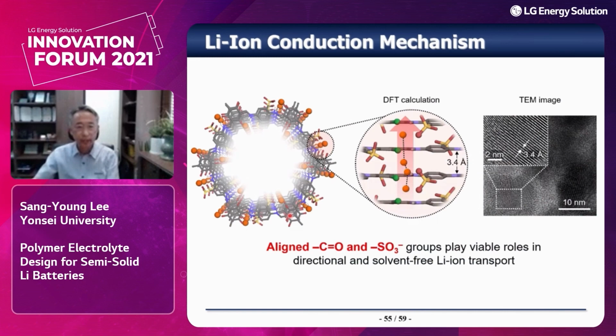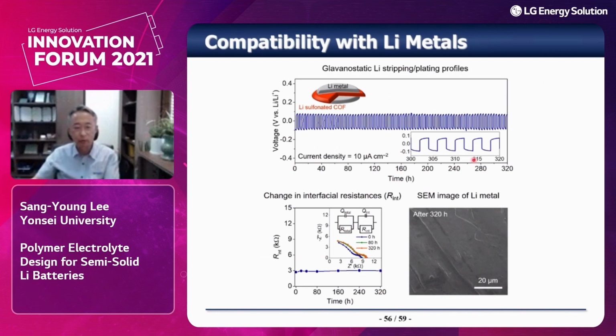Here is the DFT calculation result. The spacing between the COF layers is theoretically calculated to be 3.4 angstrom, which was experimentally verified by the TEM image like this. Therefore, we can expect the COF layers are well aligned in the through-thickness direction, and stable cycling behavior was observed.